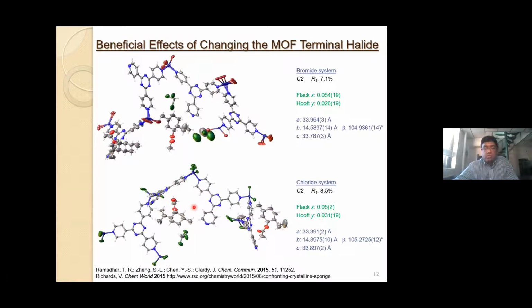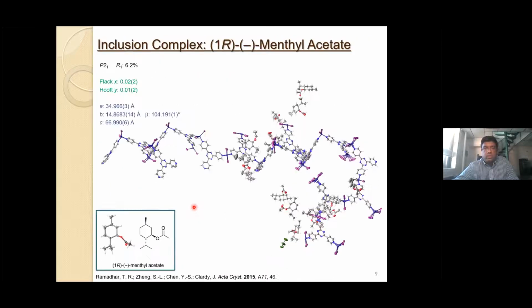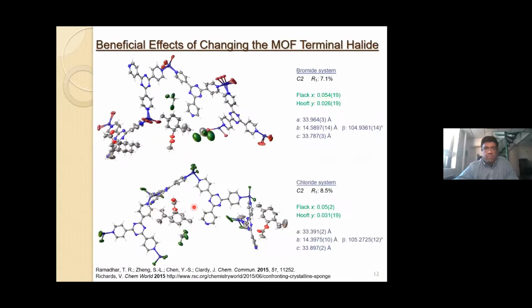But there's also one big advantage too. Remember, take a look at this, the case of including 1R-menthyl acetate in the zinc iodide sponges. You can see that this is a huge system that took 3 weeks to refine. The single crystal to single crystal transformation for the zinc bromide and zinc chloride systems wasn't as extensive. The symmetry didn't drop as much. It went down to non-centrosymmetric C2 for both. And the unit cell axis didn't double on the C-axis. So the unit cells were smaller. It was easier to refine these. It only took me a few hours, which is a lot better than a few weeks.